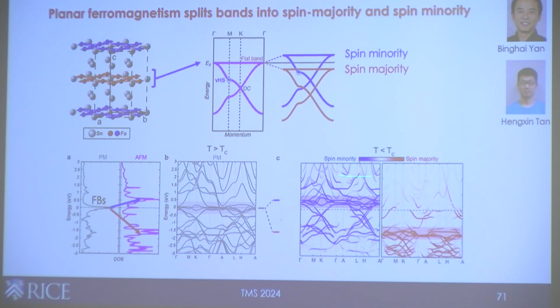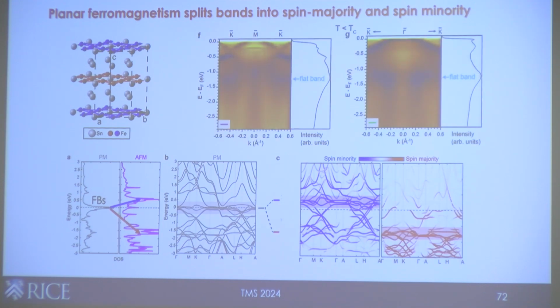So qualitatively, we can think about this picture and then ask the question: if we track through the ordering temperature, how much of this exchange splitting actually closes, as a way to gauge the nature of the magnetic order associated with the flat band. So first of all, where is the flat band? We measure at the base temperature, the lowest temperature we can measure, and in this large view you can see this peak around 1 eV below the Fermi level. That matches very well with the DFT predicted location of the spin majority flat band. So the DFT actually does a pretty good job for the low temperature phase.